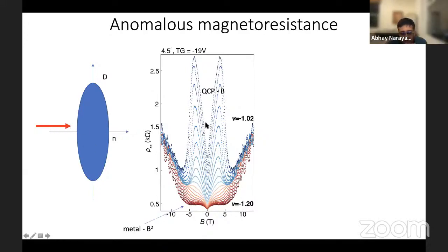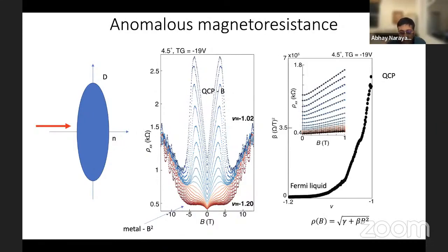But as I approach the quantum critical point, first, you can see that the response, this is not scaled in any way, this is the real response as a function of magnetic field, becomes very strong. And second, you see this very clear region of linear in B behavior that's observed. Again, this has been observed in other materials like cuprates and nickelates. And there's an ansatz that I think James Analytis and others have used to describe this kind of crossover behavior from B squared to B. So if this gamma number is large, then it's like a B squared. And if gamma is 0, then it's B linear. And you can see how this crossover from B squared to B happens as you approach this quantum critical point.